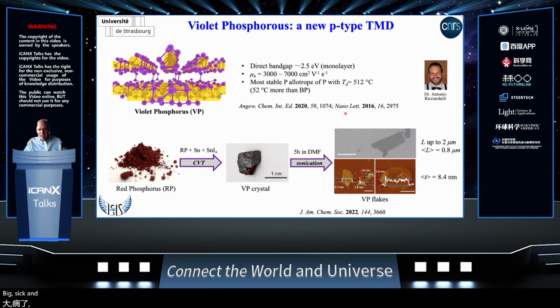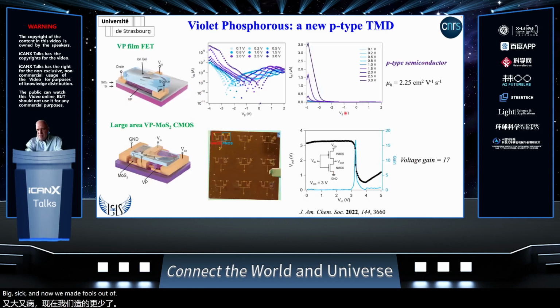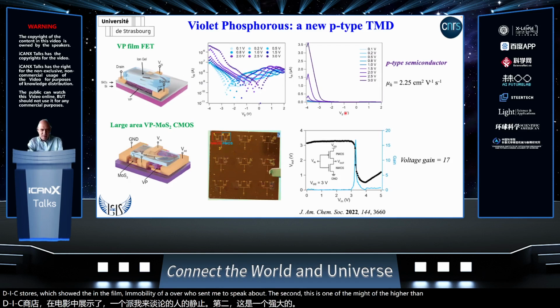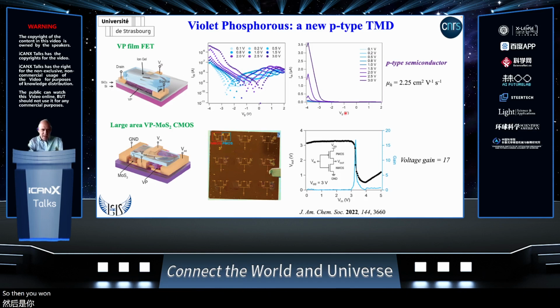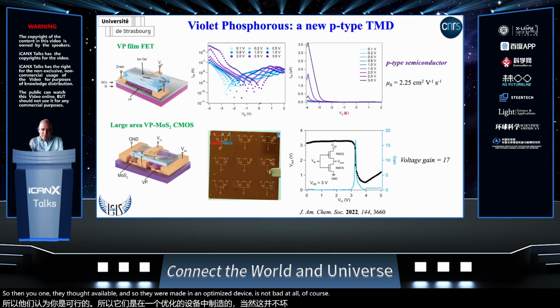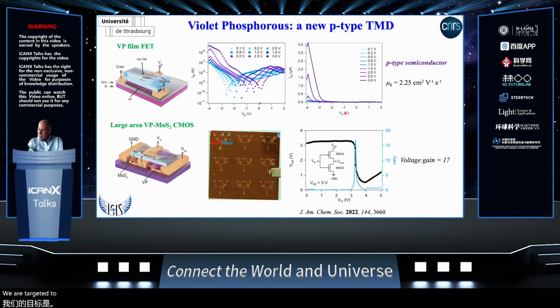And now we made films out of it. We made transistors, which showed in the film a mobility of over 2 centimeters squared per volt per second. This is one order of magnitude higher than the typical p-type TMDs. There are a number of selenium ones that are available. So the mobility in an optimized device is not bad at all. Of course, we are aiming to study the mobility of isolated flakes and see how far we can go.